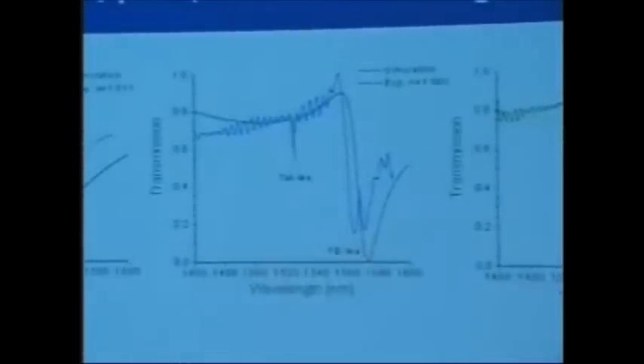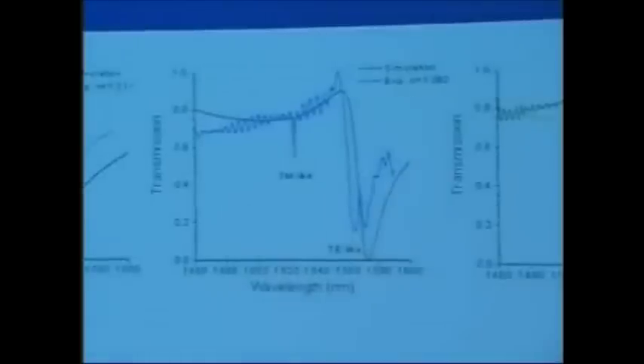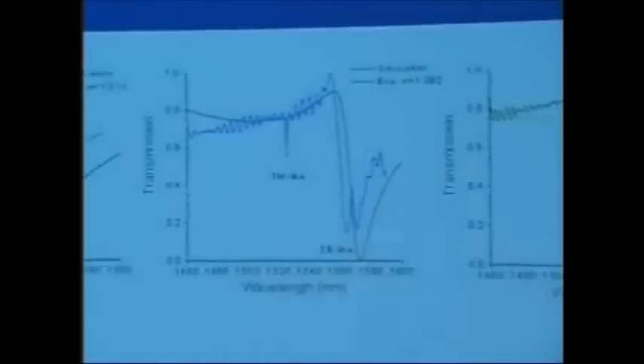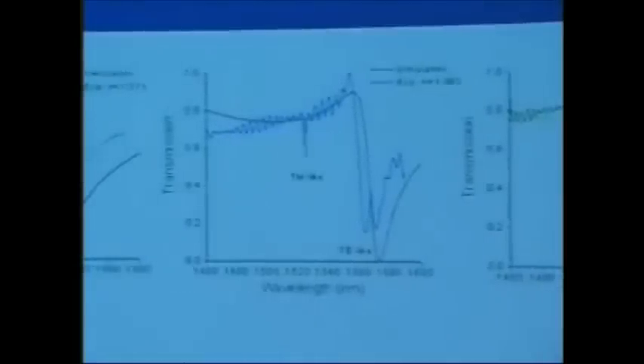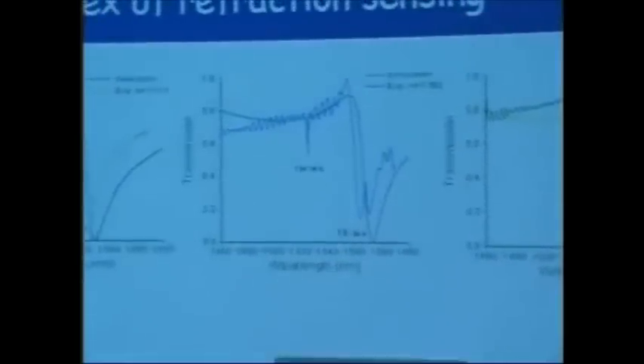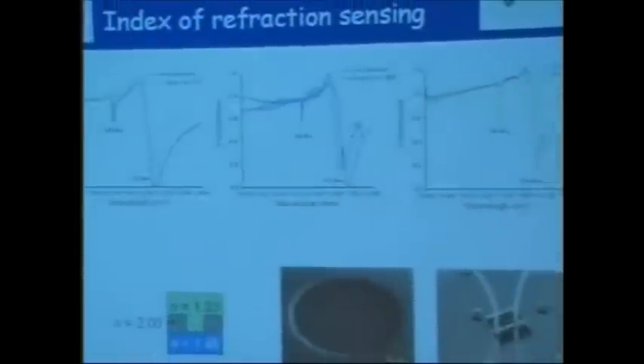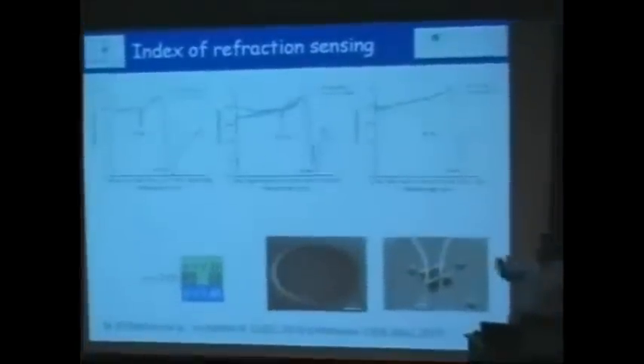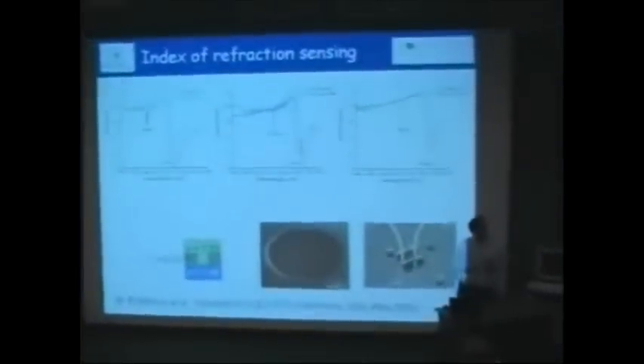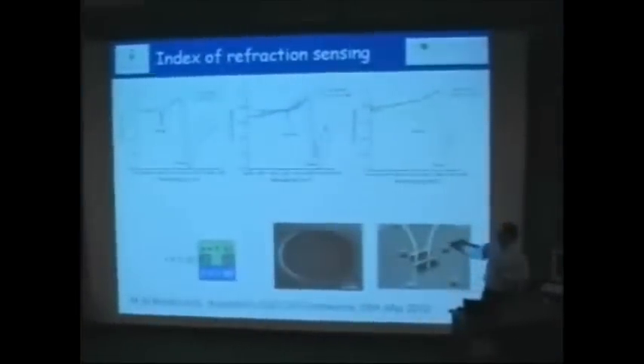You could see that the simulation predicted quite a very sharp peak in the TE-like resonance, and in the experiment it became a split peak. So that's usually due to non-uniformity in the fabrication process. But the TM-like peak was much less influenced. And the reason is, if you remember, most of the energy in the TM-like peaks sits outside. It doesn't sit inside the hole. And therefore, if you have imperfections in fabrication that are shown mainly in the middle of the hole, TM-like peaks would be much less influenced by this. So this is an example where you could use that and still get a very good biosensing.